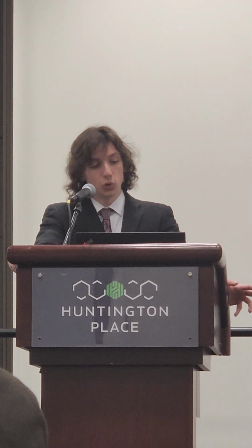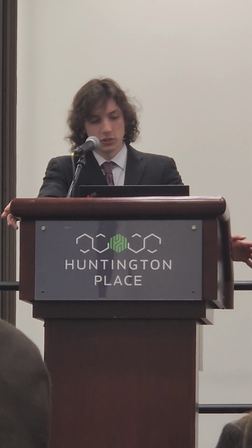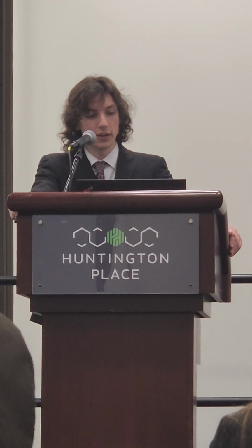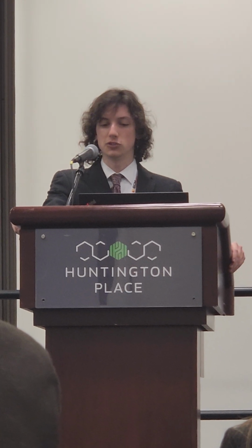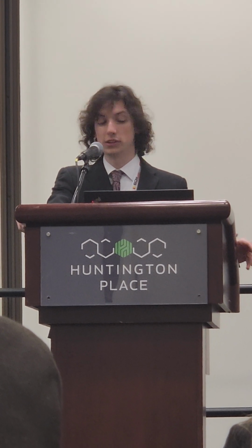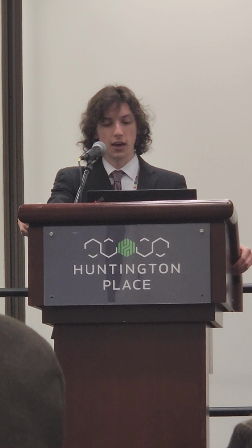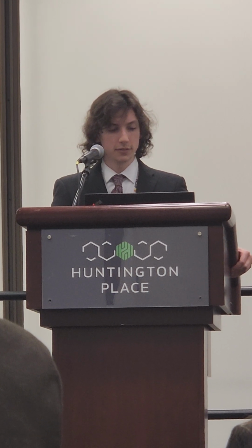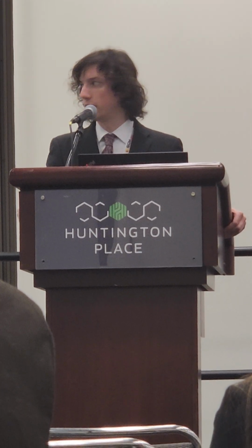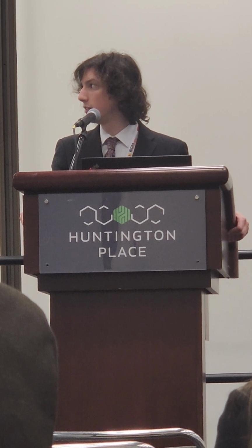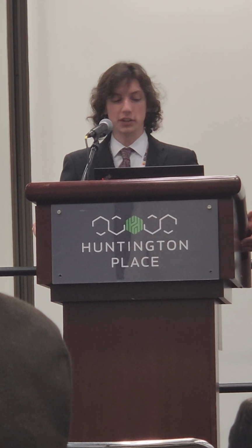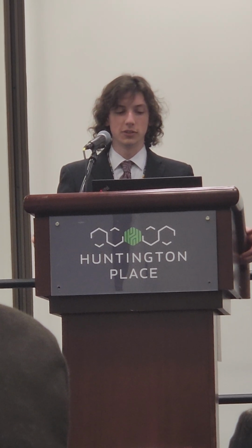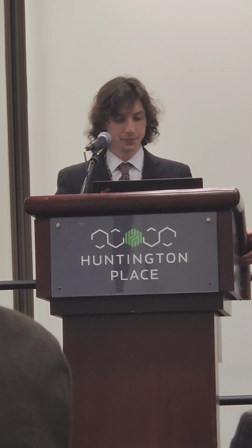Now, looking at the effects of cold reduction, similarly, grain size is generally refined with the increase in cold reduction, likely due to an increase in the amount of deformation substructures and leading to more nucleation sites for austenite. And similar between both alloys, the previous slide being the standard alloy, this slide being niobium modified. As cold reduction increases, so too does the refinement of the microstructure.